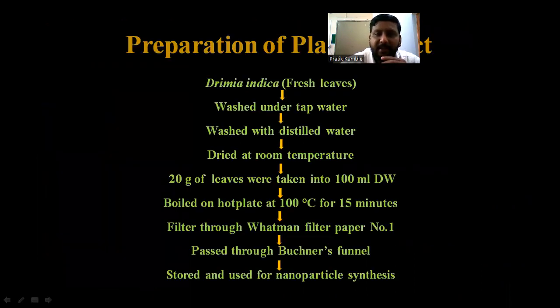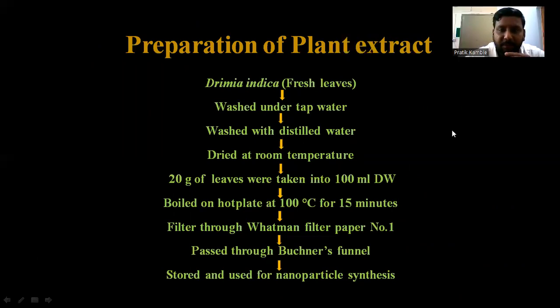Preparation of plant extract. Drimia indica fresh leaves were taken and washed under tap water, washed with distilled water, and dried at room temperature. Then 20 grams of leaves were taken into 100 ml distilled water. They were boiled on a hot plate at 100 degrees centigrade for 15 minutes. That extract was filtered through Whatman filter paper number 1. Then that was passed through Buchner's funnel and then stored and used for the nanoparticle synthesis.